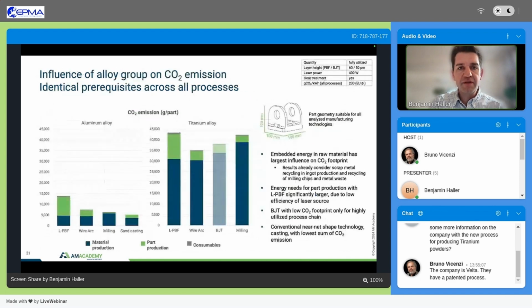So that's an important aspect. Then the second one is looking at the alloy group, and this is also important to take away. We have aluminum versus titanium, but if you would take steel, that would be quite similar to aluminum. So for aluminum parts, when we look at laser powder bed fusion, the majority of the CO2 emissions come from the printing process itself, because it is a very slow production method.